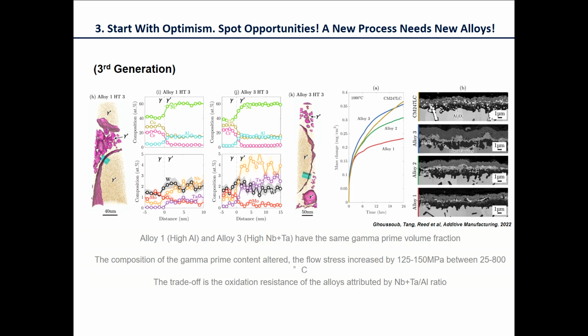We also have spent a lot of time collaborating with people. This hopefully will come across in my presentation. These are examples of atom probe maps where we are stripping away the atoms one by one and working out where they sit in the microstructure. I'll show you how we do this in a minute. But you can see here typical microstructures, predictions for the gamma-gamma prime equilibrium, and tests done of the oxidation resistance of these new alloys in this way.